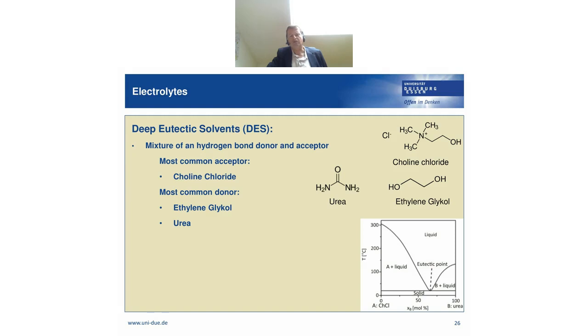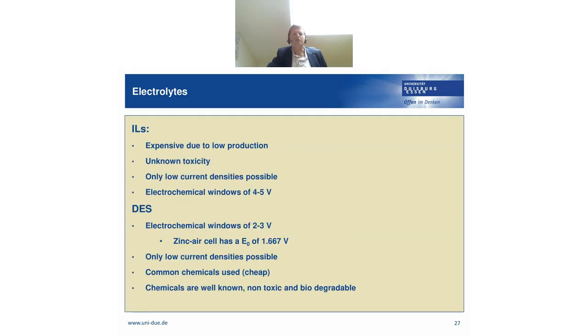And we see here a diagram where you see this eutectic point. And here again, you see the different characteristics. Ionic liquids are, of course, expensive due to low production volume. Sometimes they have unknown toxicity, but they have a large electrochemical window of 4 to 5 volt, which is very favorable. DES have a somewhat smaller electrochemical window, but it's still big enough for our zinc air cell, which has an open circuit voltage of 1.6, 1.7 volt. And DES chemicals are well known. Generally, they're non-toxic and also biodegradable.